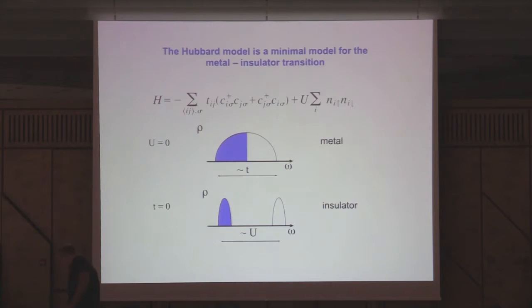So from a theoretical point of view, of course, there's no question. Our spherical cow model is the Hubbard model, which has two terms. It's very simple. It has one kinetic energy term, a tight-binding Hamiltonian with nearest-neighbor hopping, and then you have a correlation term. If you cross out that one, you consider the limit where you only have a conduction band. You fill it, you put one electron per site, you expect a metal, and of course you get a metal with a bandwidth of the order of the hopping t.